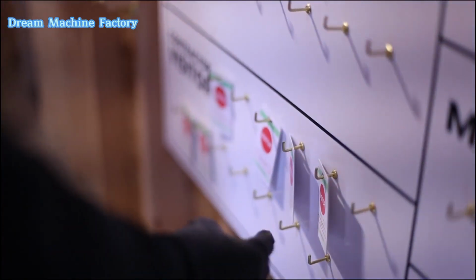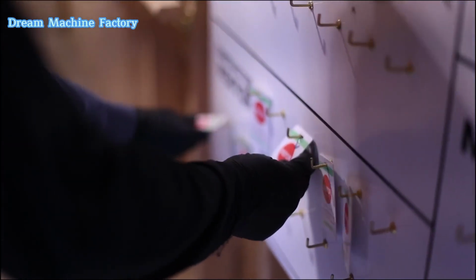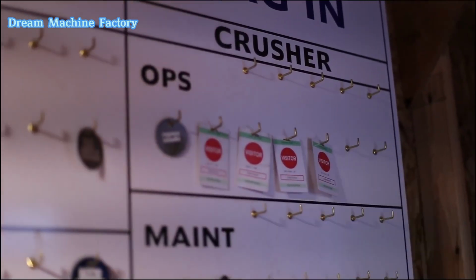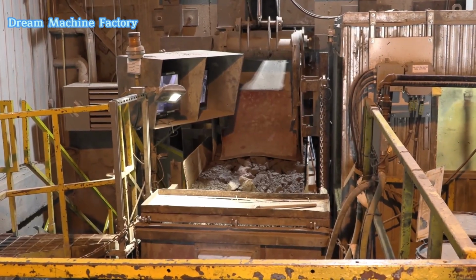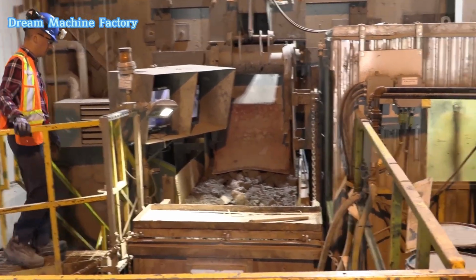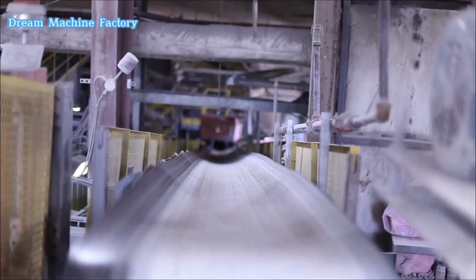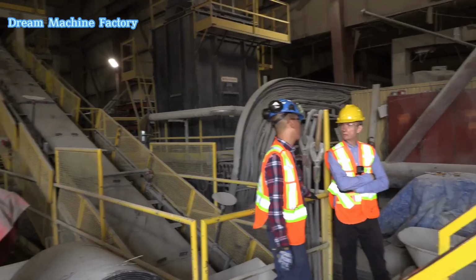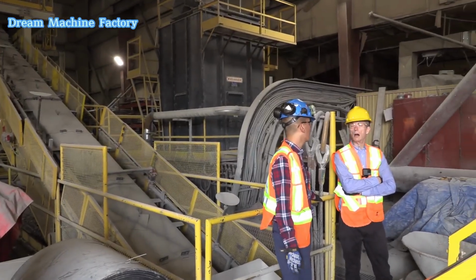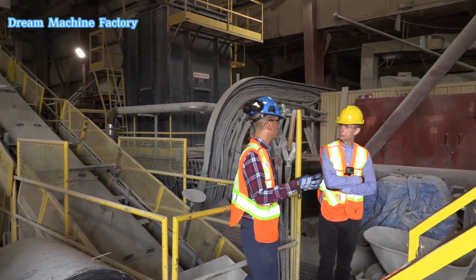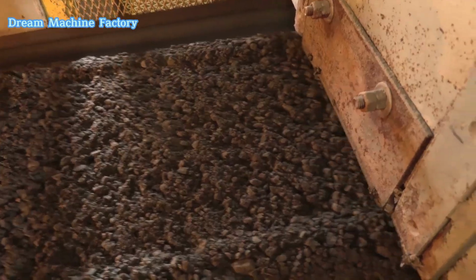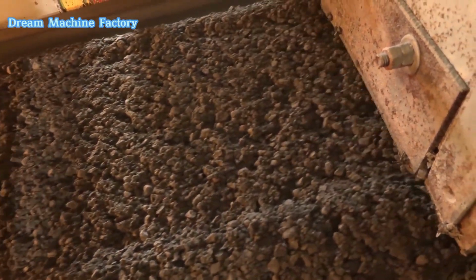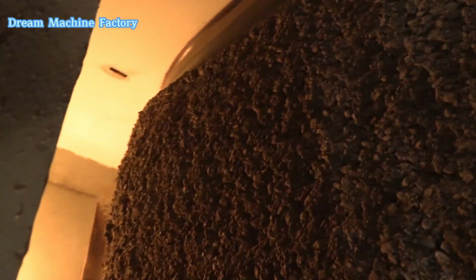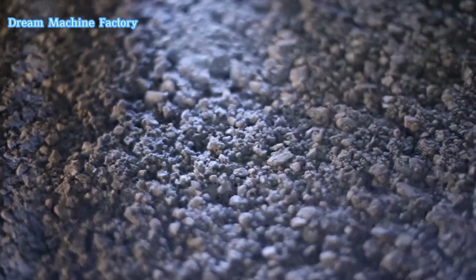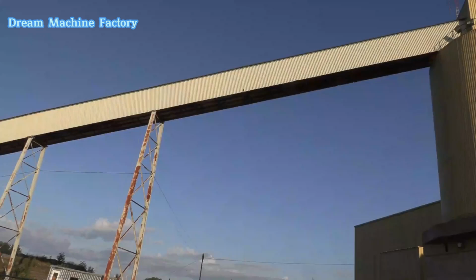Once the ore is transported to the surface via the skip, it enters a jaw crusher, where the rock is broken down into pieces roughly the size of a softball, around 4 inches in diameter. This is the first step in reducing the ore to a manageable size. The crushed material is then sent via conveyor belts to additional crushers, which continue breaking the ore down into smaller fragments. The final crusher reduces the ore to 7/16 of an inch, about the size of a Cheerio, making it fine enough for the next stage of processing.